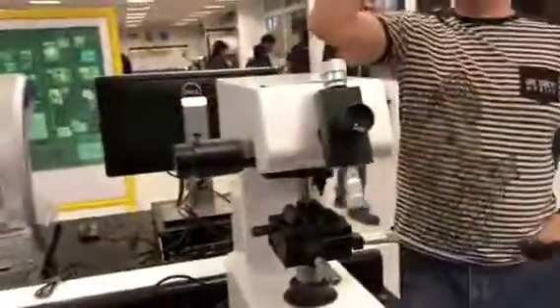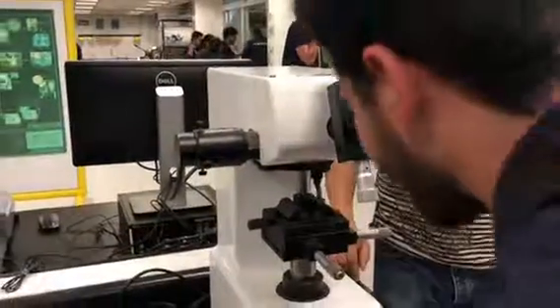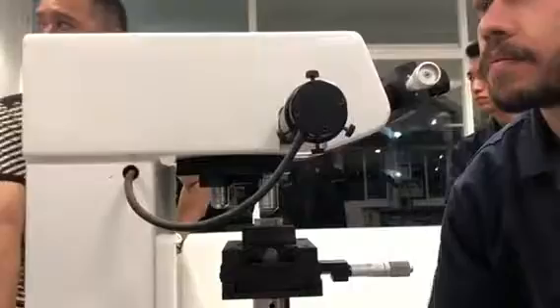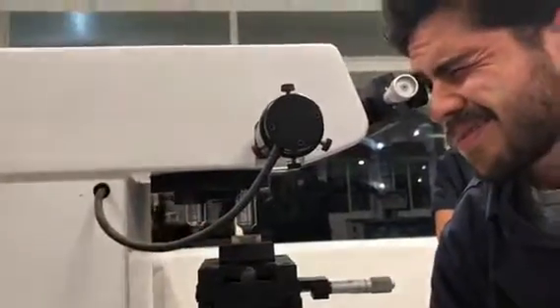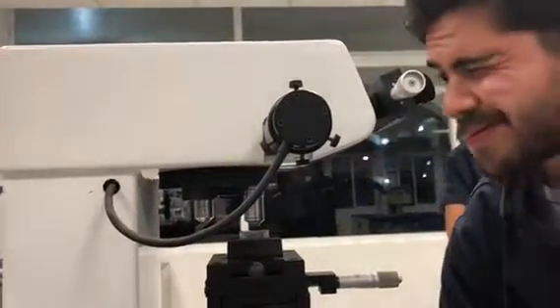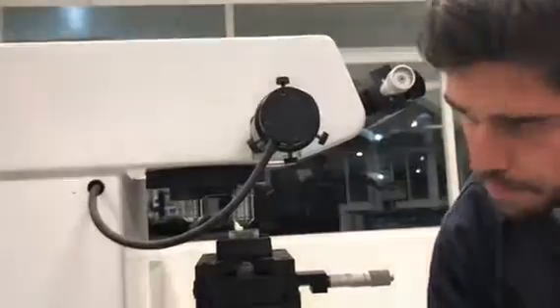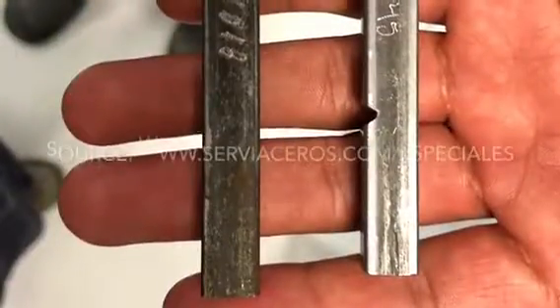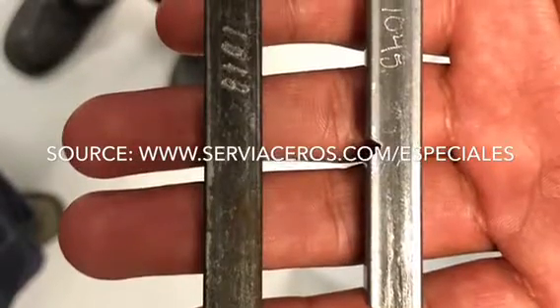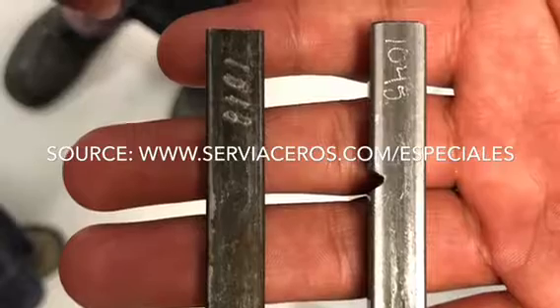This result that contradicted our initial hypothesis was researched, and because of the low carbon concentration in the composition of the 1018 steel, this type of steel softens when it is subjected to tempering. The 1018 steel does not have a conventional response to tempering. If an increase in hardness is needed, processes such as carburizing and quenching can be used.